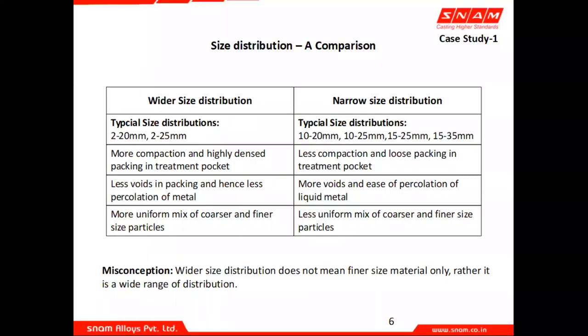Naturally, when you fill it with a funnel into your treatment pocket in the treatment ladle, it is going to be a dense compaction. When it is dense compaction, there are lesser voids. When there are lesser voids, the molten metal that you're pouring inside takes time to percolate. It doesn't just flow immediately and get into contact. When that happens, there is a delayed reaction. The delayed reaction happens, then what happens? You will have less of magnesium that is volatile and burning, and more magnesium available for nodularization. Losses of the magnesium are reduced, and that will result in improved properties.